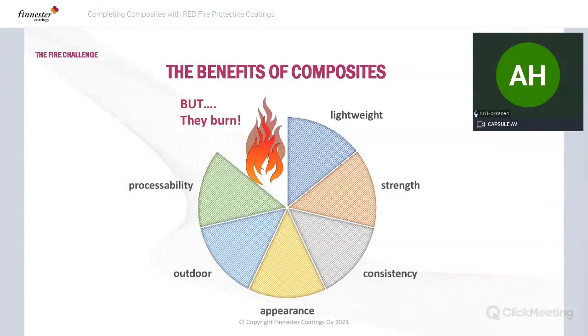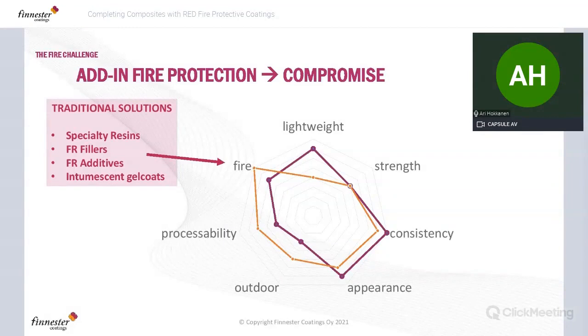But let's face it, they are oil-based and they burn. That's the Achilles heel of composites. Of course, there are fire retardant or fire resistant composites in the market, but they are more or less done with adding some fillers or additives into the resins, or even changing to specialty resins. But they usually lead to compromises in the composite. And you will lose the properties why the composite was chosen in the first place. So suddenly they are heavy, not that strong, they are brittle, not consistent. You have limited colors and gloss levels available. You really cannot use them outdoors because they absorb water and they cannot handle UV. They are high viscosity resins, high viscosity products. It's difficult to process. But yes, you will get some fire protection at some point. But you will lose the nice properties of the composite that it was originally chosen for.